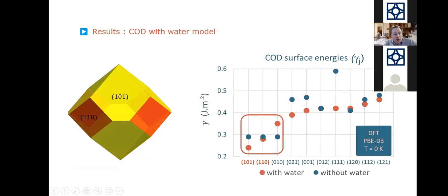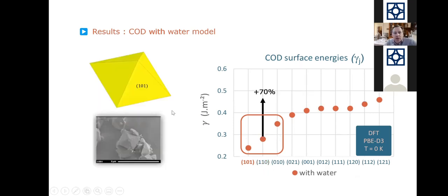In water, we can even delete one surface, but still there is this surface that we don't see at all experimentally. So this is something that is also inhibited experimentally. So we need, in fact, to correct it to obtain this structure, which is in agreement with the experiment.